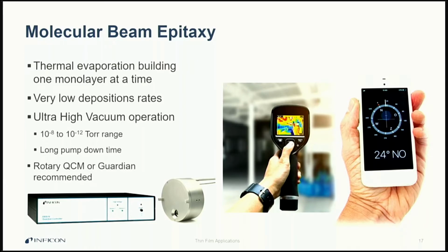And this high amount of temperature control allows the deposition rates to be run at a very low rate and actually build layers one monolayer at a time. With layers forming at such low rates, you're actually able to achieve what's called epitaxial growth, which is where the material that's deposited is actually forming a crystalline structure, which allows for great uniformity and directional depositions.